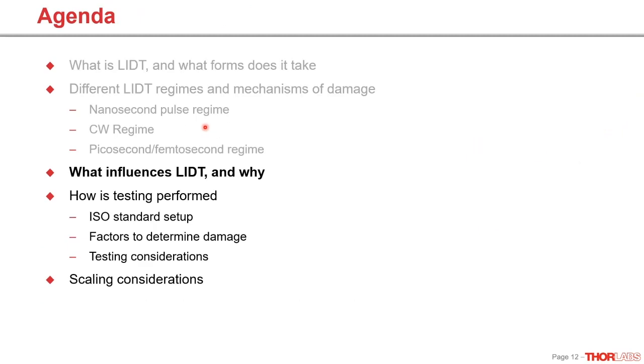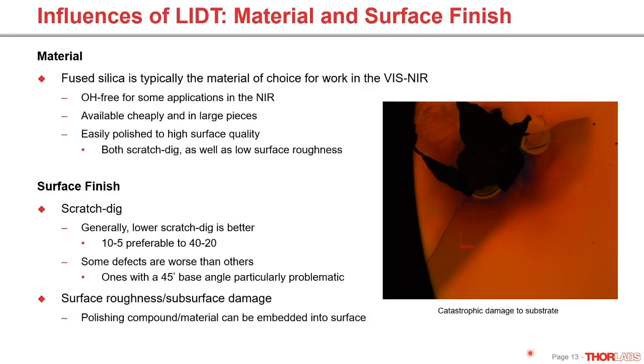So that was an overview of the different regimes and the mechanisms there. And next, we're going to move on to what influences damage threshold and why. I've touched on some of that, but let's try and get a little more in depth. So one of the big influences here is material and surface finish. Just because a lot of the light is interacting with the coating, even for a mirror, doesn't mean that the surface can't be an issue. You can see here, we have what is catastrophic damage to a substrate. You can see the coating damaged, and then this is literally a hole in the glass. So that's obviously much worse for component integrity than just some damage to the coating.